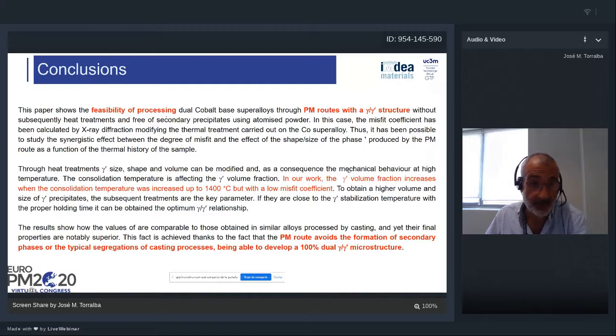The consolidation temperature is also affecting the gamma prime volume fraction, as we have seen. And in this work, the gamma prime volume fraction increases when the consolidation temperature was elevated to 1400 degrees, but with a relatively low misfit coefficient, similar to the previous one obtained for the 1250, but a little bit lower. To obtain higher volume and size of gamma prime precipitates, of course, the heat treatments are the key parameter. So with this heat treatment, we can try to increase this gamma prime size and distribution.